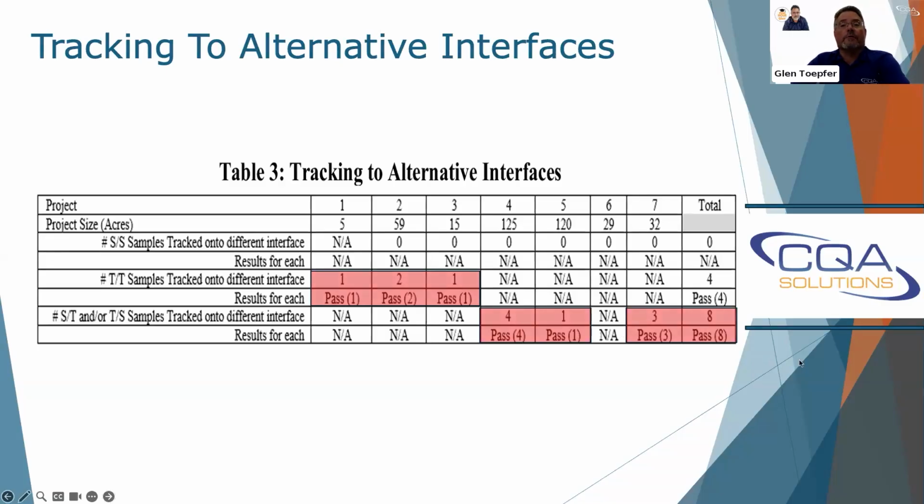I think we're tracking things in the wrong direction, or we're not taking into account similar material interfaces that have failed. We're going chronological, and that was always the belief that, something goes wrong with a machine, you go chronological and you have it fixed. But I think this data shows otherwise. You may not have it fixed. You really got to be evaluating it by interface.